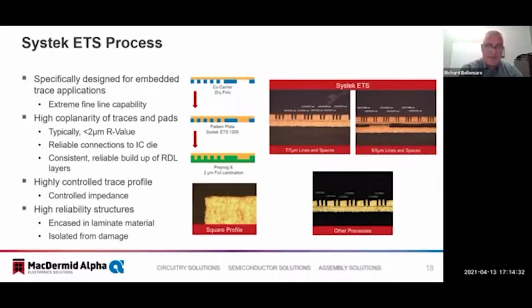This process is a pattern plate process that provides a very high coplanarity of traces and pads, typically less than 2 micron height differential. And it's important for reliable connection to the IC die with minimal warpage, to prevent die cracking, as well as consistent, reliable buildup of the subsequent RDL layers underneath. The resulting trace profile is highly controlled and square for controlled impedance applications, and the process is production proven, and all process components are totally analyzable, for complete system control.